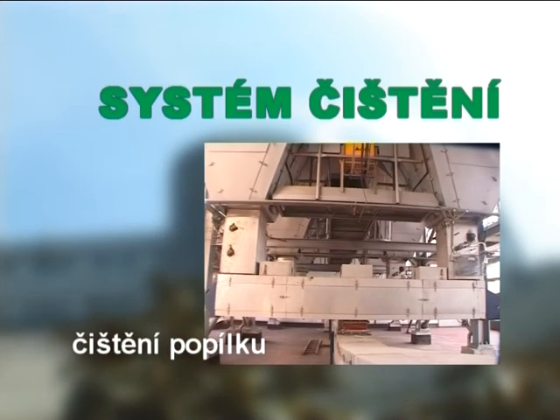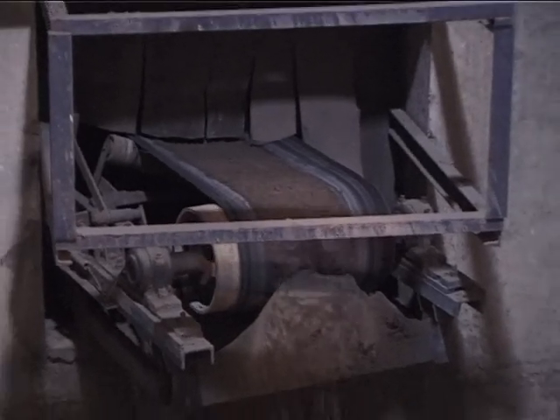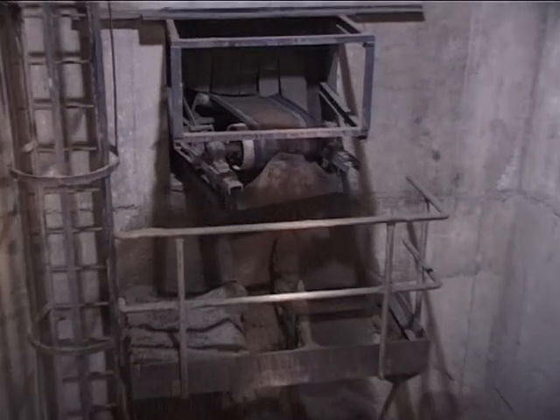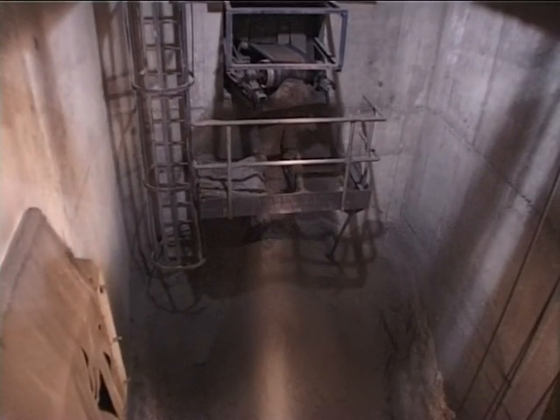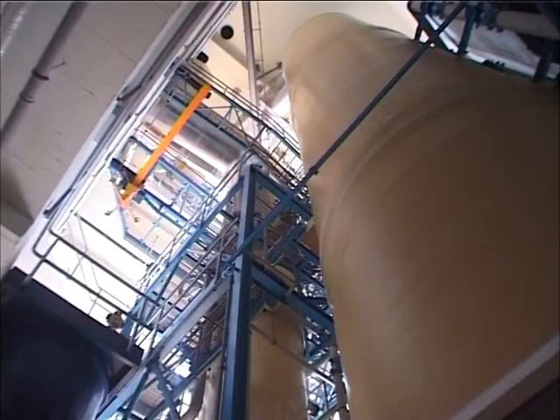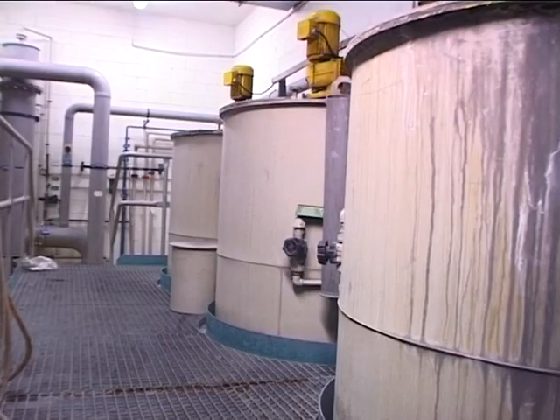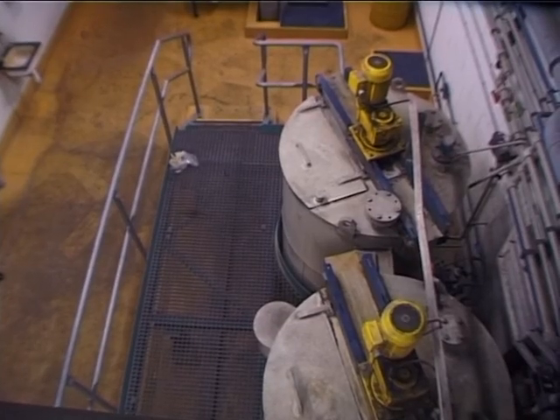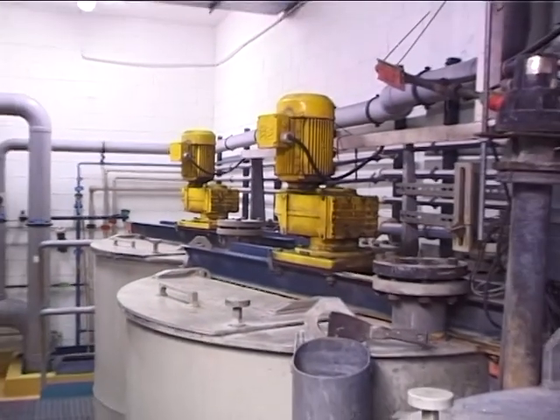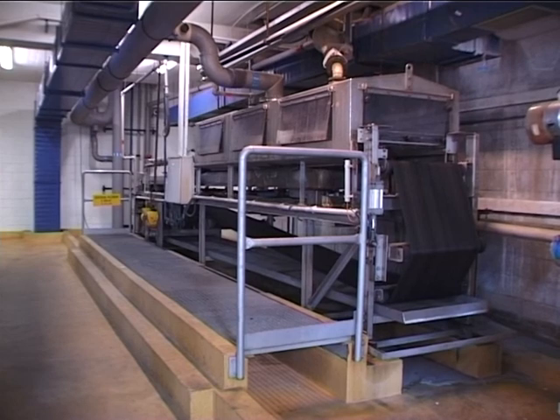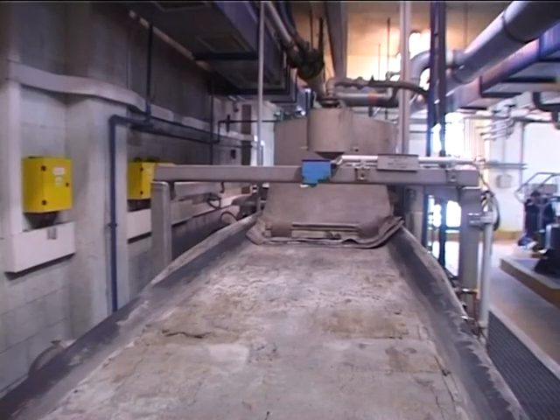Besides flue gas, waste incineration also produces cinders and slag. To stop raw cinders exhibiting their hazardous qualities, soluble salts and extractable heavy metals are removed from them. This is done with the aid of acidic water, which comes from the flue gas washer, more specifically from the first stage, that is the quench. Cinders stored in the silo after their removal from the flue gas are administered to a trio of extraction tanks. Here they are infused in water with pH 3.5 and a temperature of 65 degrees centigrade. Next, they are brought for dehydrating on a vacuum filter belt.